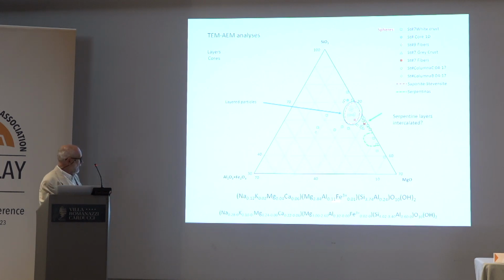The average clay structural formula is that. It's mainly a saponite, but I prefer to say it's a saponite-stevensite because we don't know if there are vacancies in the octahedral structure. And here you have the range of variation of the different cations.